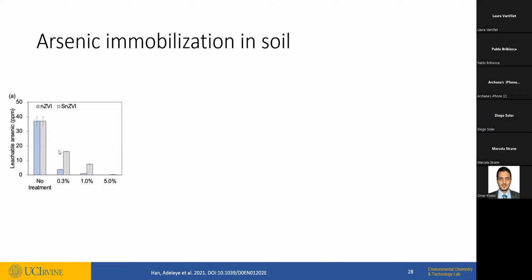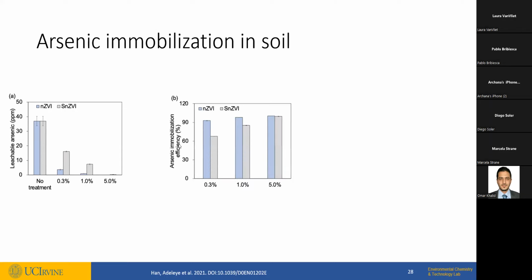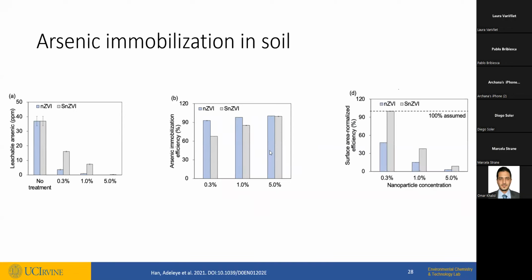And with nanoparticle introduction, the amount that was leachable decreased substantially. And if you add more nanoparticle, you get better performance in terms of immobilization efficiency, this is what the data looks like. And again, if you want more performance, you can add more nanoparticle, but there is somewhat a limit to the amount of nanoparticle you want to add to a soil that you want to grow food in, right? Because at that point, the nanoparticles themselves can start to exert some negative effects. So this data was collected over 7 days, and we think it should be longer than that for us to say confidently that the nanoparticles can actually immobilize arsenic.